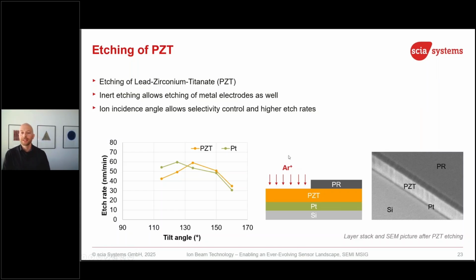And we etch this PZT layer with argon, or could be also other inert gases. And on the left graph, we plotted the etch rate of PZT and platinum. First, what you see, it's changing versus the angle of incidence. Second, it's about the same, even though at smaller angles, PZT is etching rather slow and platinum much faster. And if you go to higher angles, it's changing. So basically, we can tune the selectivity from lower than 1 to greater than 1 if it's about the PZT to platinum.